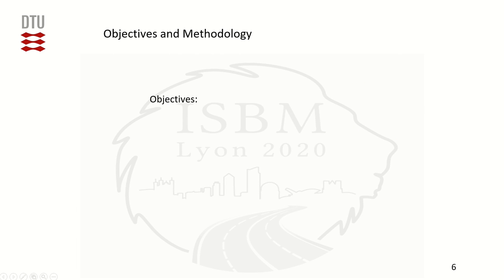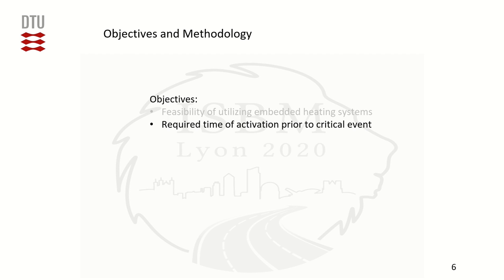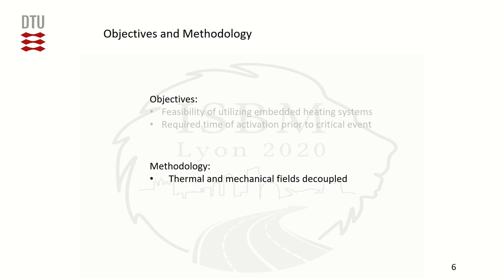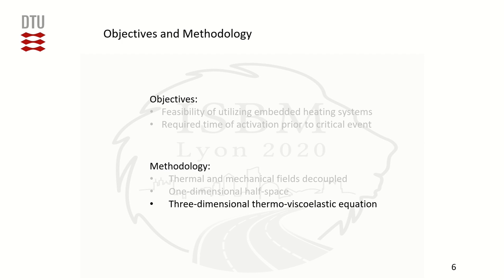The objectives of this paper are to first demonstrate that the overall idea of utilizing such embedded heating systems to deter low temperature cracking is attainable, and to second, based on the depth of embedment and the output power of the heating system, determine the required time of heating activation prior to failure to mitigate low temperature cracking. To this end, computer-based calculations were carried out in which the thermal and mechanical fields were decoupled. The thermal field considered the one-dimensional heat equation applied to a half space, while the mechanical field was acquired with a three-dimensional thermoviscoelastic equation.